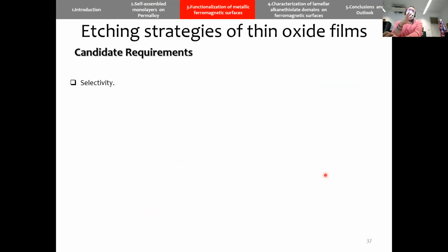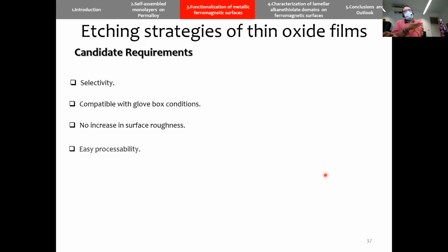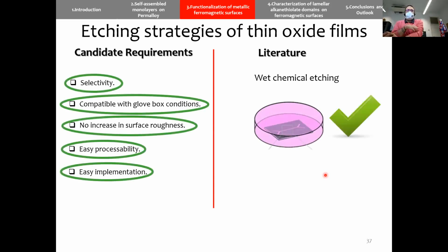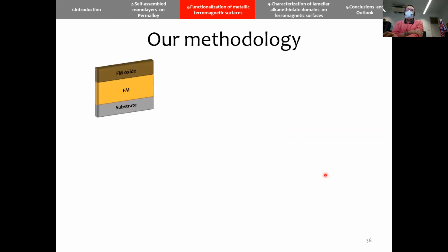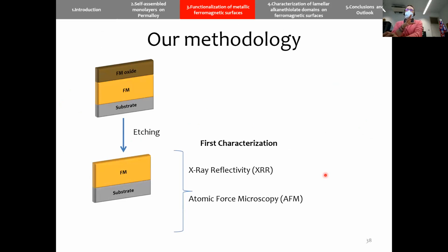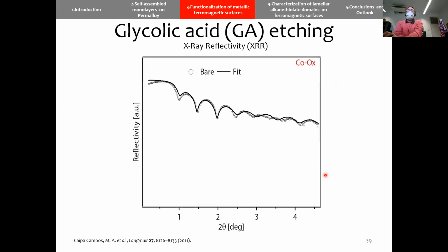So in order to obtain this, we are looking for a candidate that can show selectivity compatible with the glove box. It should not increase the surface roughness, and should have easy processability and easy implementation. And so in literature, all these characteristics are answered by wet chemical etching. In this case, we perform the etching. We study the thickness by reflectivity as already introduced, and also we take a look at the morphology of the structure of the surface.